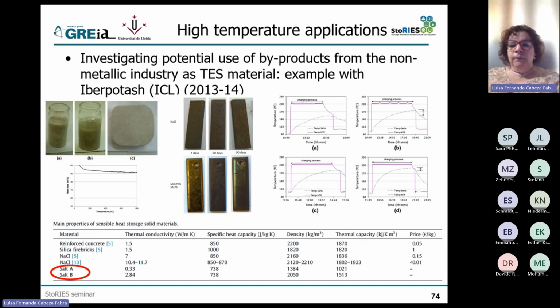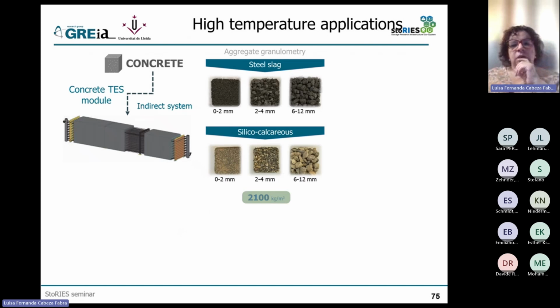This is one study that we did, and we were able to publish. Not everything that we do with industry can be published, but the idea and the concept, I wanted to bring it to you. Another one is we have been working also with concrete for sensible energy storage at high temperature. To do that, as I told you before, the biggest challenge is that if we use standard concrete with Portland cement, when you go higher than 400 degrees C, this storage collapses. This is why buildings collapse when there is a fire. So now our challenge is to produce a concrete that can withstand 700, 800, 1000 degrees C.